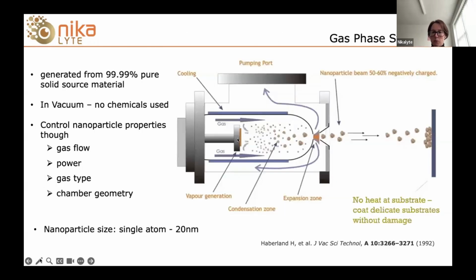This distance here between the magnetron and the exit from this aggregation zone is effectively equivalent to the time that those atoms of material spend in this chamber. So by changing that distance, we can change the residence time of the atoms and the growth time of those nanoparticles. We can also change the geometry, which is basically the shape of this chamber here. And all of these parameters are controlled by the user. They're things that can be changed either as the process is running or by mechanical changes before and after the process is run. And they will all impact the properties, the size, the density, the structure of the nanoparticles that are formed.